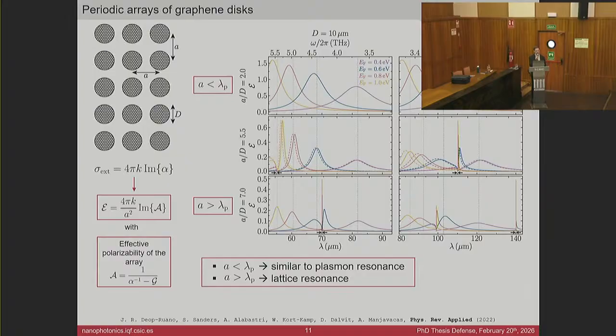And very importantly, we also have some kind of rotational Doppler shift in which the response of the nanostructures is Doppler shifted. And this is something that connects a bit with the case of the particle moving at relative speed relative to the thermal radiation bath, in which we see that these effects arise from a Doppler shift. In this case, we have a different Doppler shift, but it's also responsible for these torques that we observe.